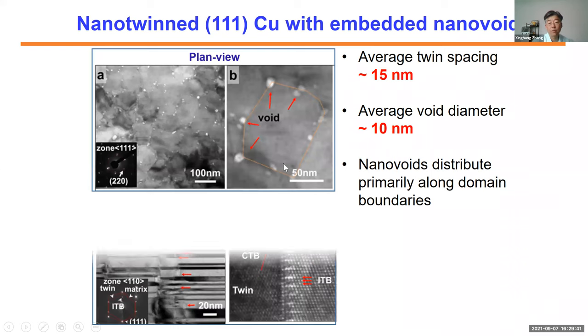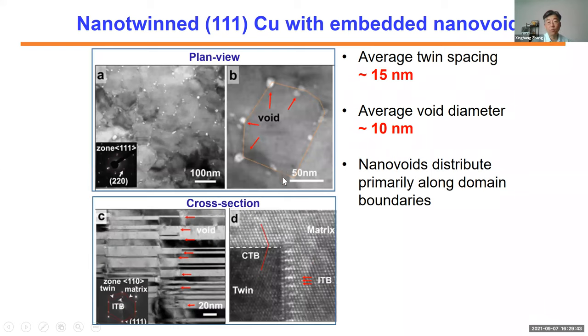And so then you ask me, where are the nanotwins? You don't see twins from the top-down view or plan view. You see them from the cross-section. From the cross-section, you can see the twin boundaries, the twin boundary layers, and the average twin spacing is about 15 nanometers, and the void diameter is about 10 nanometers. And these nano voids are mostly distributed along the vertical twin boundaries, or grain boundaries, if you will. The void size is very small, 10 nanometers.